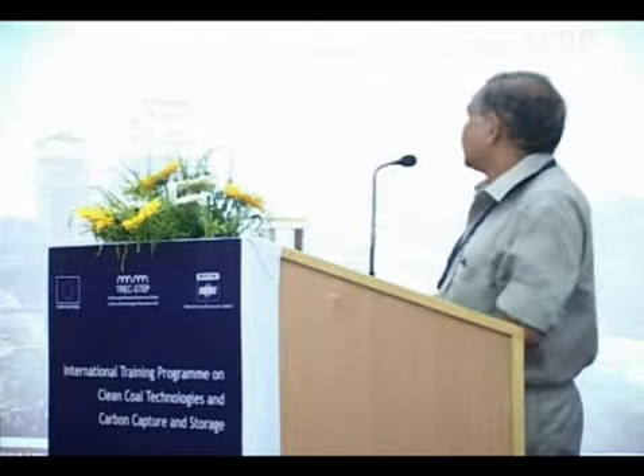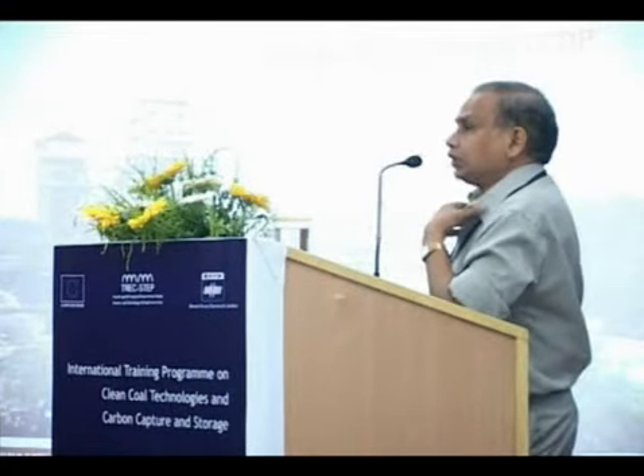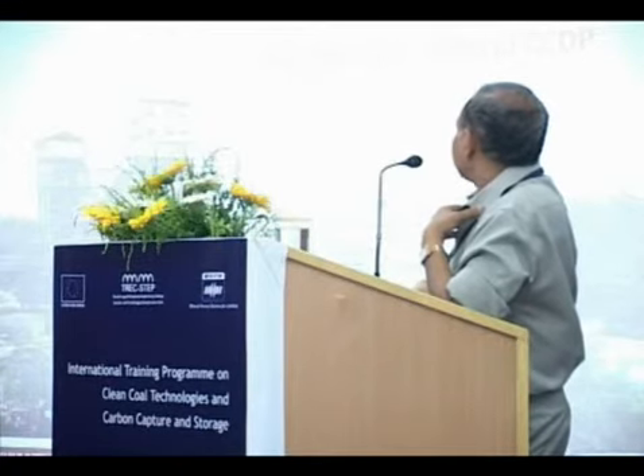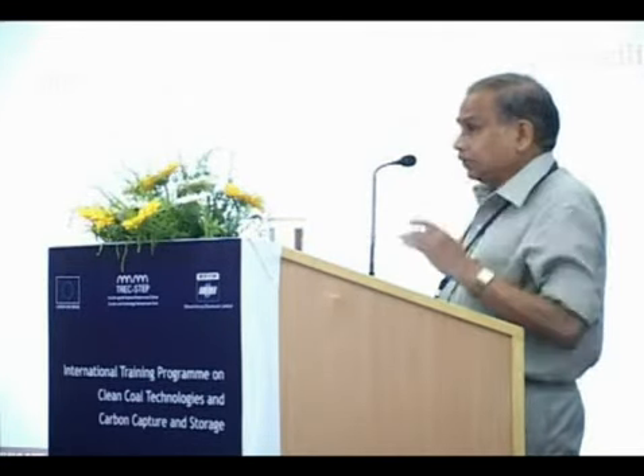Apart from this, now we come to the IGCC. In IGCC, you can see BHEL as early as the 80s tried to put up a demonstration plant of 6.2 megawatt using a moving bed gasifier, and that was not successful. So then we went for pressurized fluid bed gasification, because the fuel has to be cleaned before it is put into the turbine. The fuel gas, what you call syngas, is produced by partially oxidizing the coal in a gasifier. Now when we adopted the moving bed gasifier technology in the 80s, we produced tar and phenol.